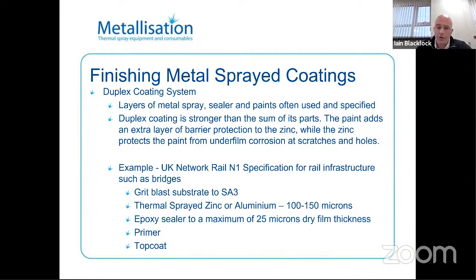An example of a coating specification in the UK is the UK Network Rail N1 specification. This is used for infrastructure and bridges. So it's a grit blast substrate to SA3, thermal spray zinc or thermal spray aluminium for 100 to 150 microns, epoxy sealer to a maximum of 25 microns dry film thickness, and then a primer and a top coat. And that's used on pretty much all of the infrastructure for Network Rail in the UK for the rail network.